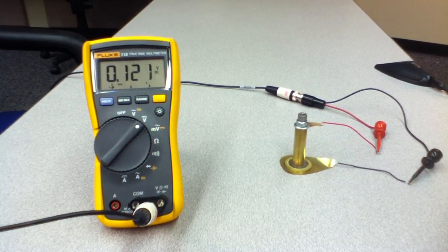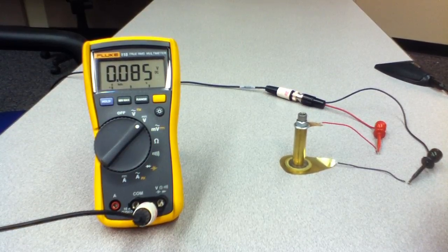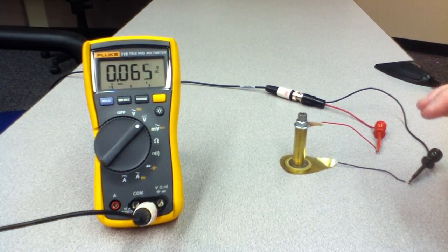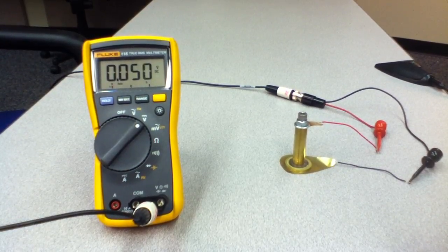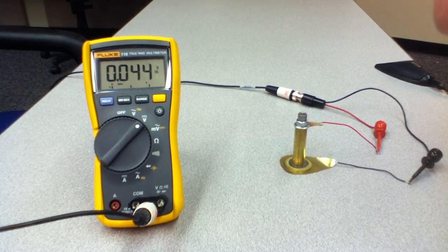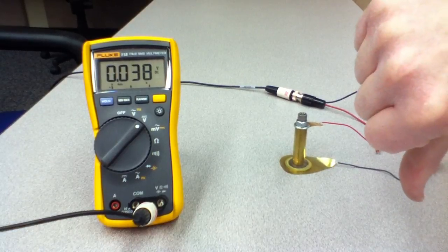Notice that the polarity was negative — the voltage produced was negative. This is a very nice test of a ceramic material. If you don't know which direction the polarization vector is, connect a voltmeter to it, heat up the material, and if you create a positive voltage, that means that the polarization vector is in the direction that you've connected the electrodes from negative to positive. If it's negative, as in this case, it means that the polarization vector is in the opposite direction, in this case from the positive down to the negative electrode.